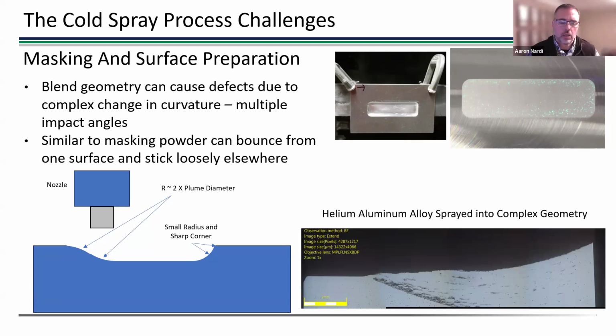If you go much smaller than that, you will start to get particles that bounce and stick somewhere else, and that's where you start to get defects forming, porosity, and so forth. So I've got a couple images on the right-hand side here kind of showing that. Upper right, you see an aluminum spray. This was a helium sprayed aluminum material, so very high quality normally. But because we're spraying into this milled pocket, you're getting these defects that are forming right around the edge of that.